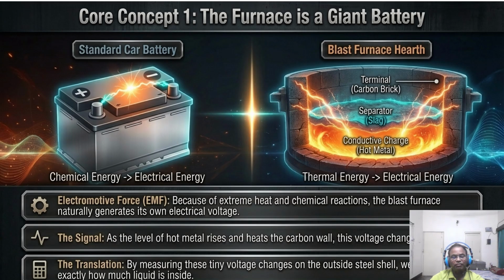As the level of the hot metal rises and hits the carbon wall, this voltage signature changes. By measuring this tiny millivolt fluctuation on the outside steel shell, we can calculate exactly how much liquid is accumulating inside. While that's the passive signal, we also have an active method to get even cleaner data.